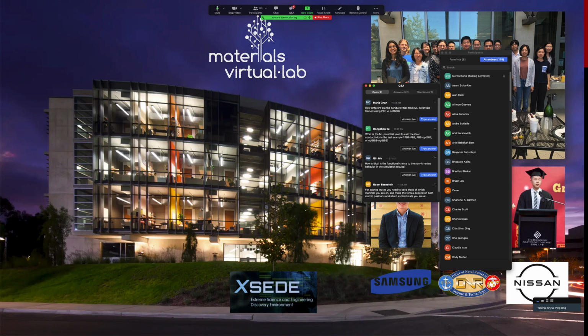Now, recently there have been additional developments where you do some form of active learning to select the structures that you are going to incorporate back into the training set to further improve the accuracy. We have experimented with that, and those work phenomenally well. Now the convergence of the machine learning interatomic potential is much faster. We can do that with even fewer structures, and we can also get a good sense of how far our machine learning interatomic potential can be extrapolated. People like Alex Shapeev have done a lot of work in this area for his MTP potential, and that's what we have been using.